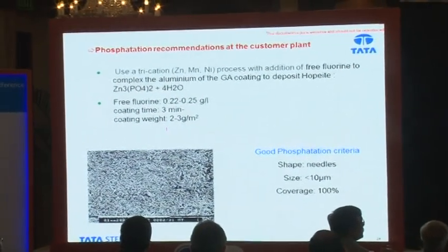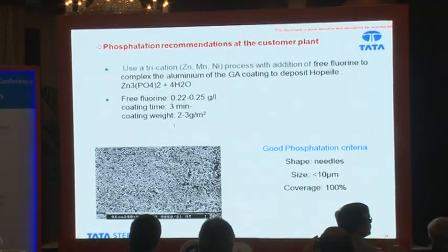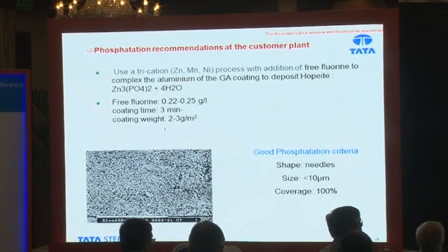In the case of coated steels, both galvanized as well as galvanneal, there is a tendency to have a thin alumina layer on the surface. Now this is very important: that particular alumina layer has to be digested, and this can be digested only by fluorine or hydrofluoric acid. So a small amount of fluoric acid has to be put, otherwise you don't get the phosphatation right, and if your phosphatation is not right, then your corrosion resistance, the perforation corrosion which I talked about, can be compromised.